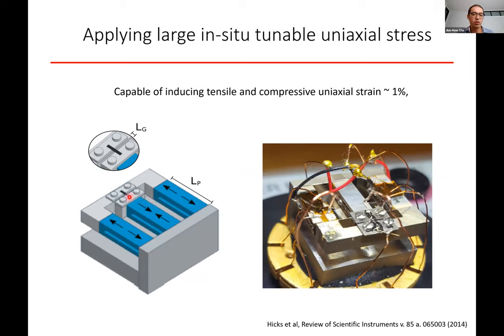When you glue a crystal across these aluminum plates, then either moving the plates away or moving the plates closer together, you're applying strain up to 1%. Obviously there are many ways of applying strain to a material, and a lot of experts are in the audience. For example, Peng Chen and Stephen Wilson have developed this technique of applying uniaxial pressure and then doing neutron scattering experiments in situ.